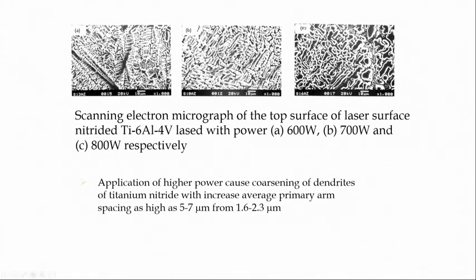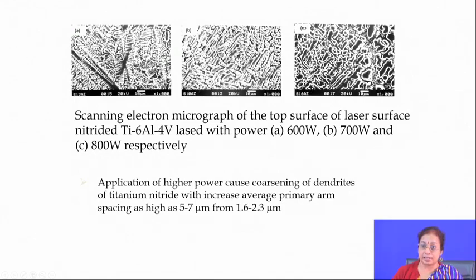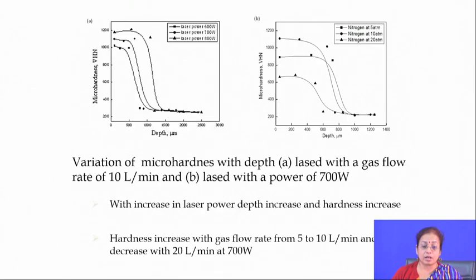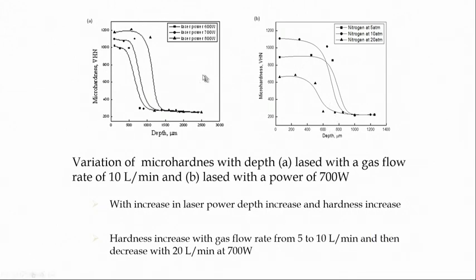So, it was observed that as we go on increasing the power, the area fraction of the dendrites increases, and the dendrites are mostly very long in nature, particularly when the temperature or laser power is very high. On the other hand, whenever it is very low, you will find that the dendritic arm spacing is quite low because of the very high cooling rate. So, you can play with the process parameters to get different kinds of microstructures, and these microstructures are very good in improving the hardness of the surface to a large extent.